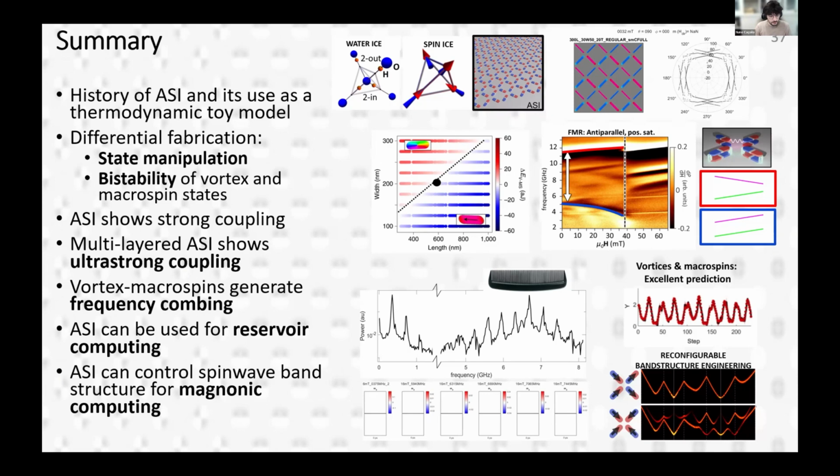Yeah, so as I mentioned, if you make them very thin, they start to thermalize, meaning that they will fluctuate with temperature, which some people do. So some people make them very thin, like on the order of nanometers. In that case, they're trying to use temperature to reach the ground state. They can go up to, it also depends on the width and the length of your islands.